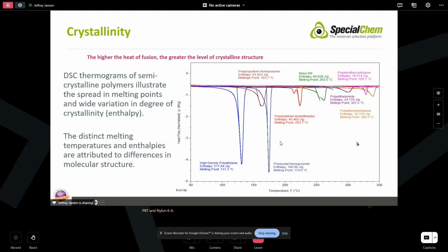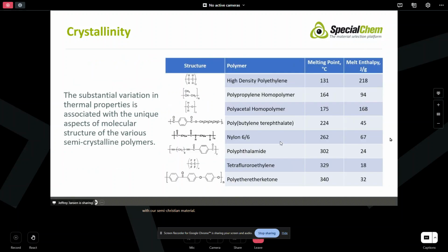So again, we can understand how crystalline a particular grade of material is. This is extremely effective for looking at high-density polyethylene. We want to understand two things about polyethylene typically. What's the molecular weight of the material? We typically get that through melt flow rate. And we want to understand crystallinity, which can either come through doing density or specific gravity testing, or, I think more effectively, by doing DSC. And you get an actual number to understand that crystalline level. So again, crystallinity is something we certainly want to look at with our semi-crystalline material. And again, differentiating a variety of materials.